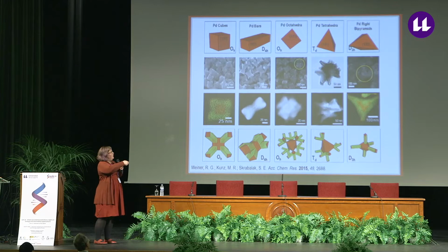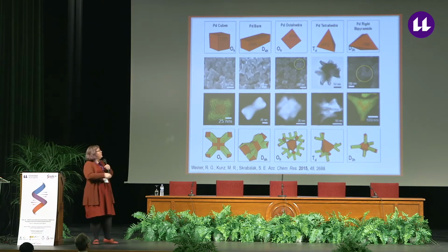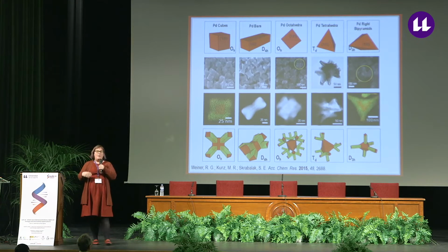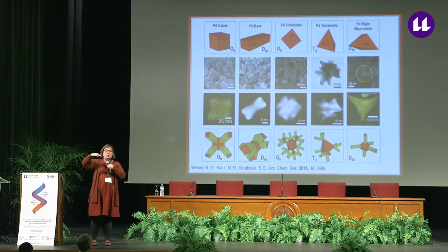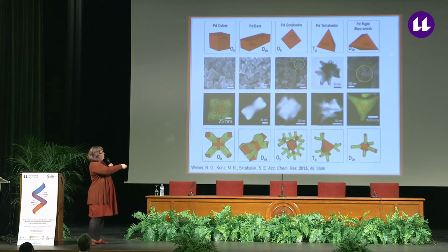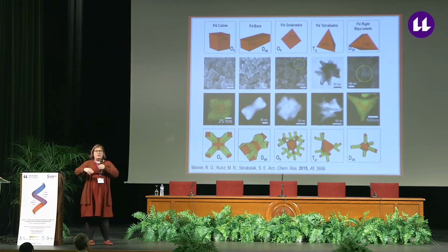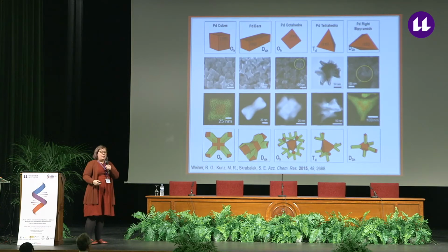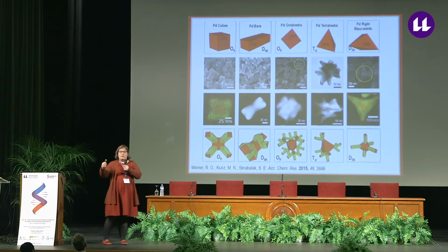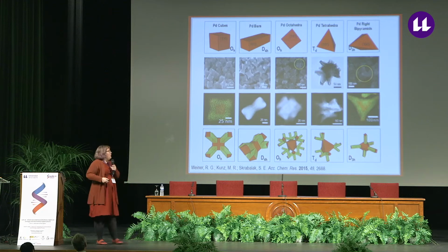These 4 structures on the left, they're all single crystalline seeds, whereas the right bipyramids are actually singly twinned. There's a twin plane that bisects through the 3 equatorial vertices to give 2 single crystalline domains. And when the overgrowth process occurs, we end up with 2 axial branches and then 3 equatorial branches where the twin plane continues through those 3 equatorial branches. So the axial branches are proceeding in 1-1-1 directions, but the equatorial branches are in the 1-1-2 directions.